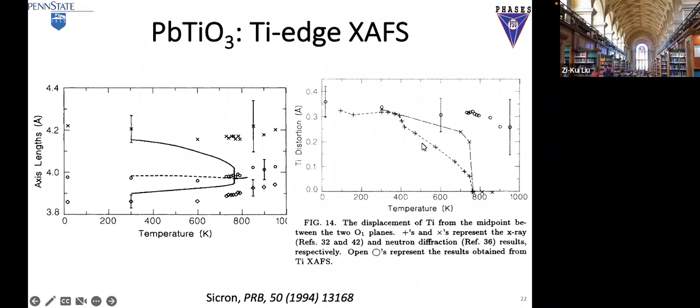Yeah, no, the cross is X-ray. Both are crosses, one for neutron, one for X-ray scattering. It shows that at the transition temperature, they go to 0. That's right, no polarization. However, if you look at the individual titanium cell, the polarization stays at all temperatures. It never disappears. So that means that the Landau theory is macroscopically correct, but microscopically incorrect. It did not represent reality, what the atom does.